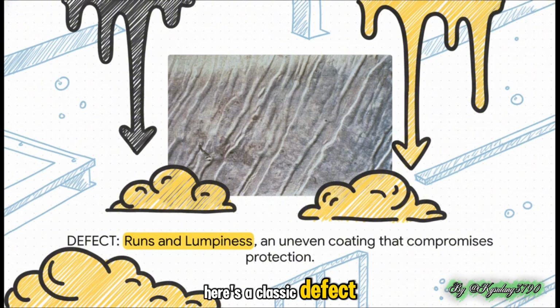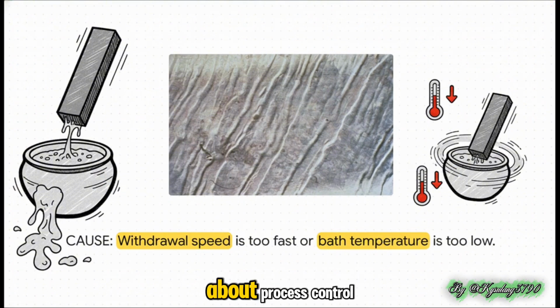Here's a classic defect. See those thick drips and all those uneven surfaces? This is what's known as runs and lumpiness. And obviously, it messes with how uniform that protective coating is. The cause here is usually about process control. If the steel is pulled out of that zinc kettle too quickly, the extra zinc just doesn't have enough time to drip off properly. Or, on the other hand, if the bath is a little too cool, the zinc is thicker, less like water, and you end up with the same lumpy result.